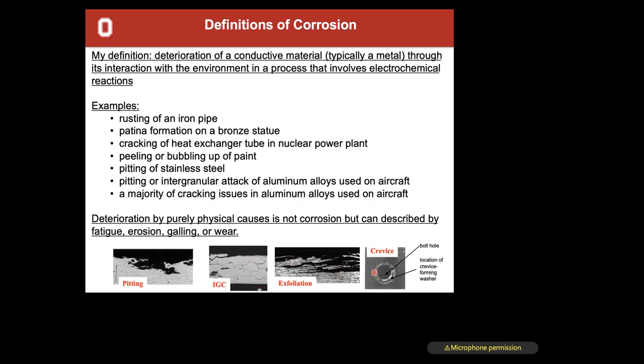And then crevice corrosion is something that's very common. So this came from a material where there was a bolt that was down, and you can see that the bolt head underneath of it, there was attack because of crevice corrosion. So anytime you have a small, tight space where some electrolyte can get in or some environment can get in, you can get accelerated corrosion there as well. So these are just different images of how corrosion can look, and it can look different depending on the material system and the environment that you're in.